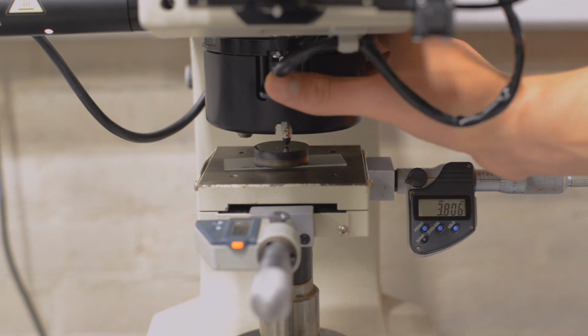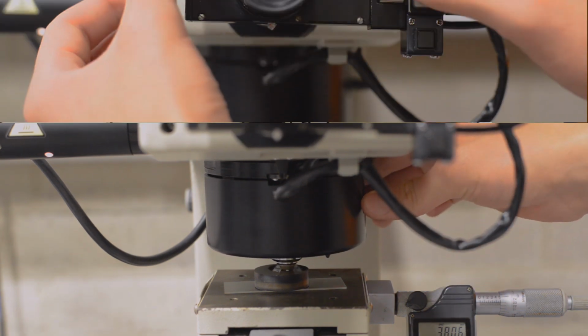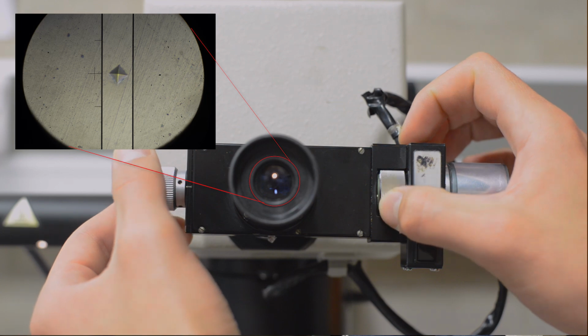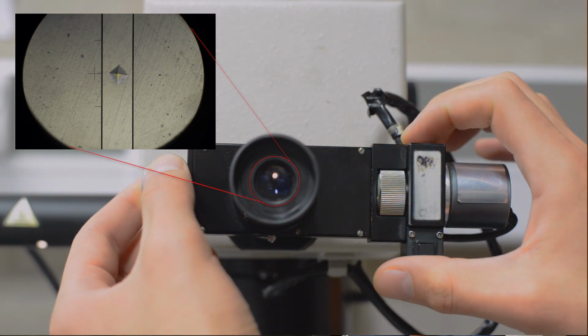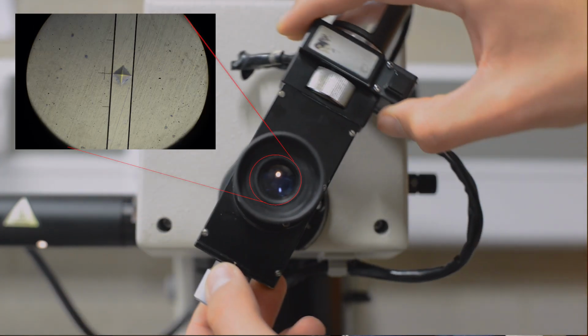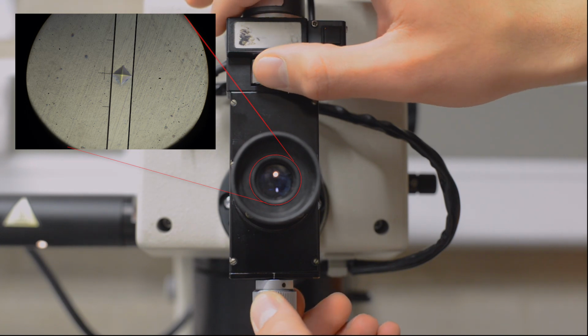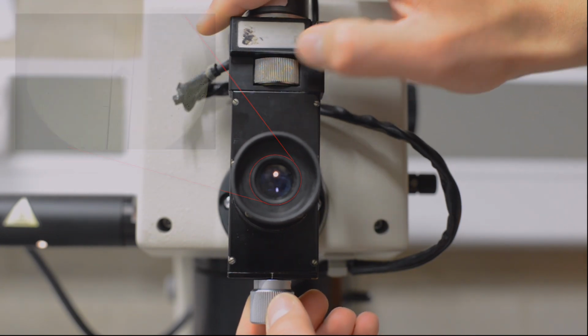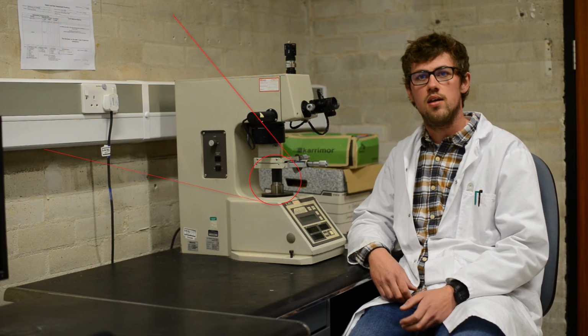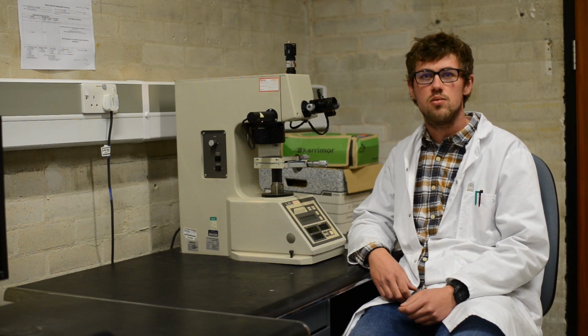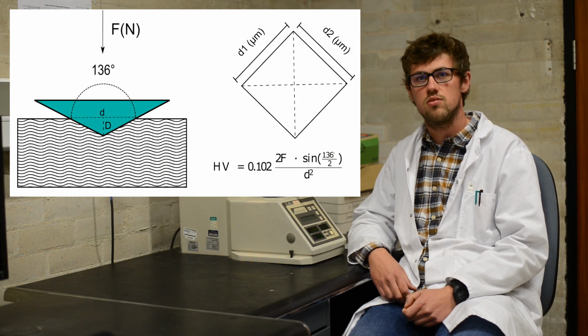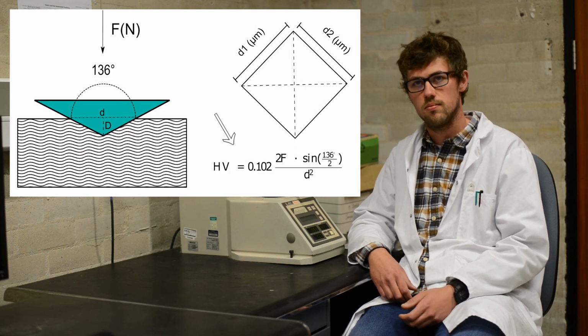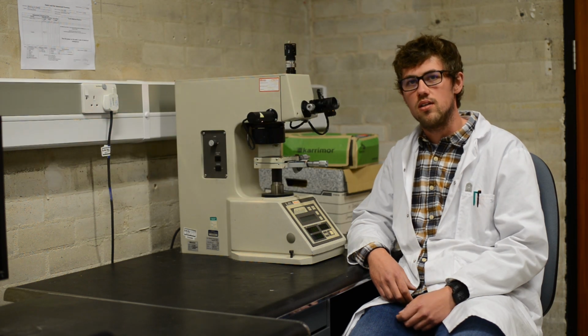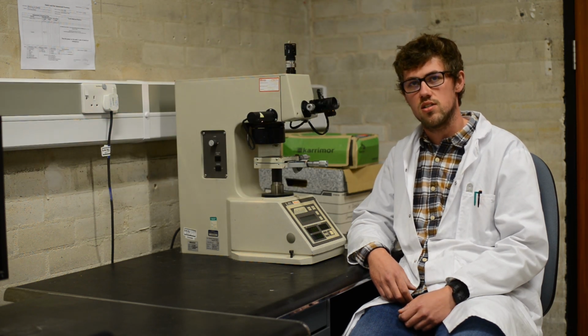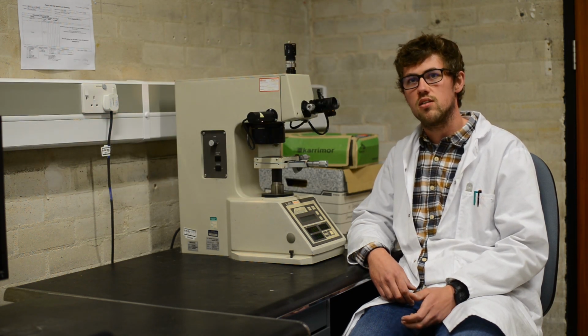Once you have applied the desired load to the sample with the indenter tip, the next step is to measure the size of the indent to enable the hardness calculation. As you can see, you will need to measure the width of your indent in both orientations. And then once you have done this, the machine will use these to calculate the hardness value using the equation shown here.